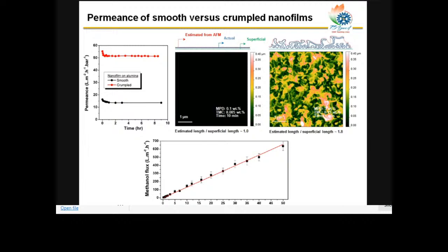And on the very bottom, the methanol flux under pressure was linear, which indicates this thin film is highly stable under high pressure application. Even if you apply 50 bar across the membrane, your methanol permeance was linear. That means depending on the amount of liquid you want to process, you can choose your applied pressure to make the process faster.